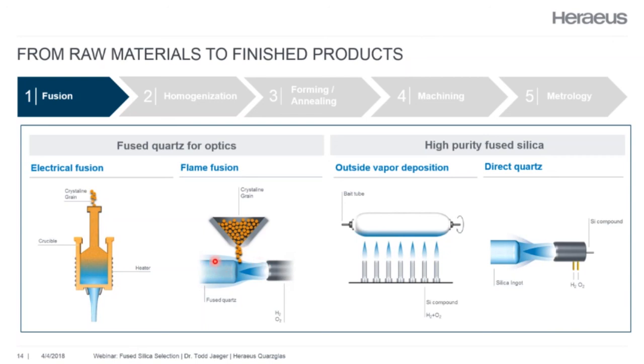The grain is heated to a very high temperature, where the crystalline structure actually breaks down. The grains then fuse into an amorphous silica material, and at this point, the material would be a fused quartz. The downside for this process is that any impurities that you would have in your raw material and your crystalline grain are going to be baked into the final product, so to say. So metallic impurities, for instance, can be an issue with this formation technology. In order to produce a material that is high purity and has much, much lower impurities, we would go with a flame hydrolysis technique. There are 2 techniques that we utilize.